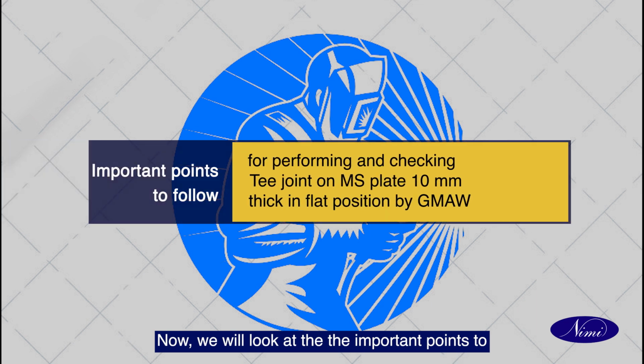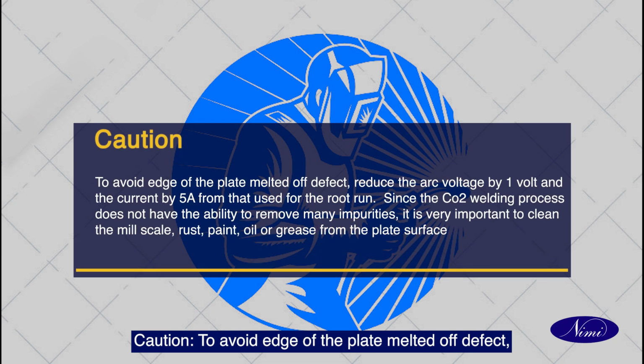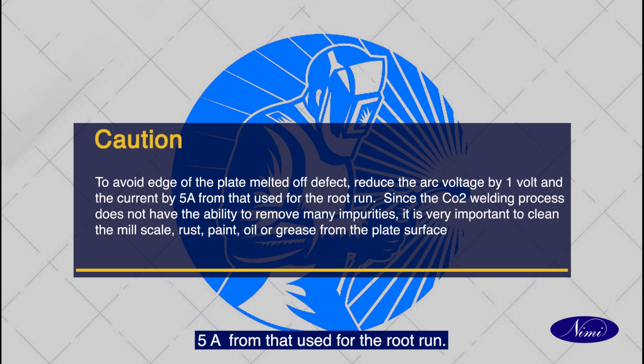Now, we will look at the important points to follow for performing and checking the T-joint on MS plate 10 mm thick in flat position by GMAW. Caution: to avoid edge of the plate melted off defect. Reduce the arc voltage by 1 volt and the current by 5 A from that used for the root run.